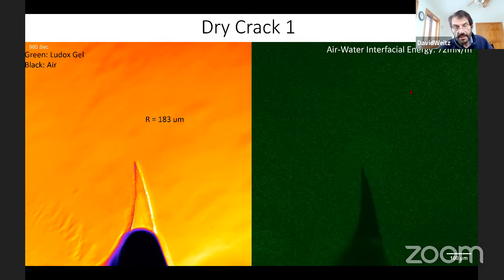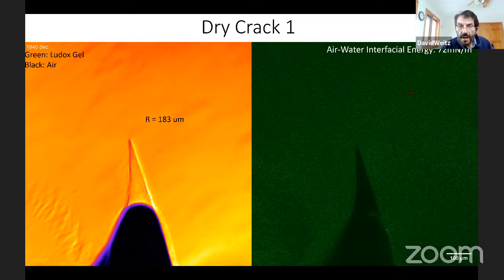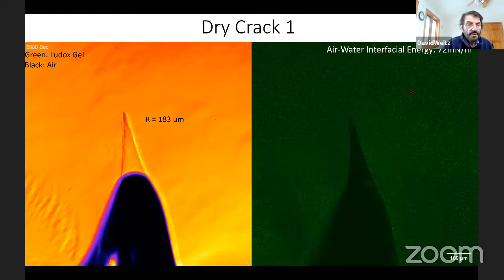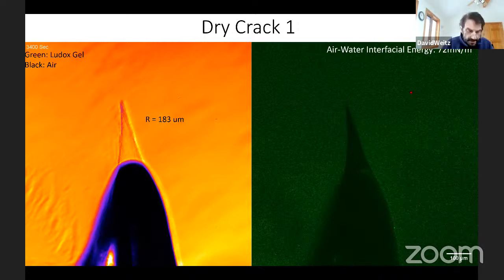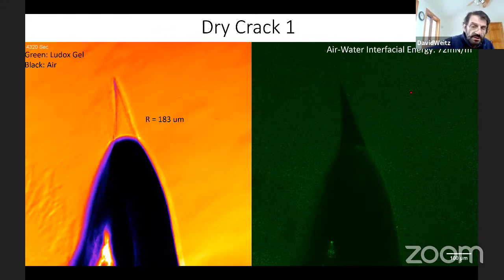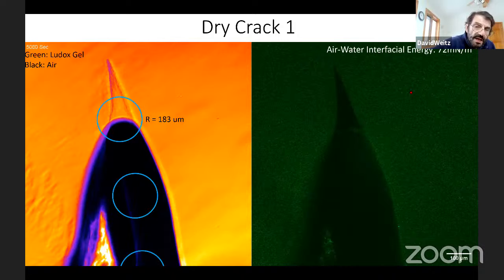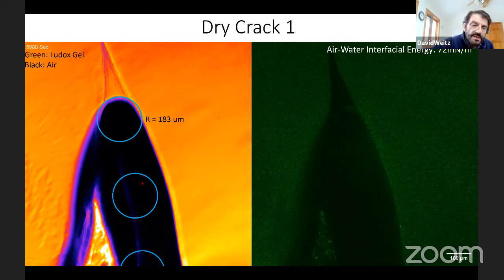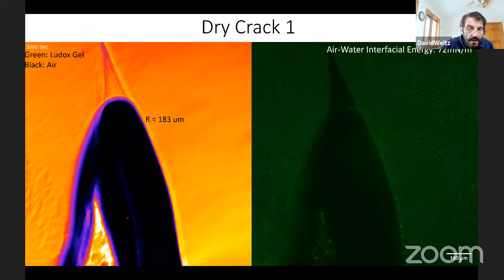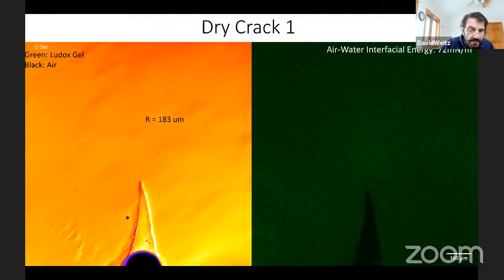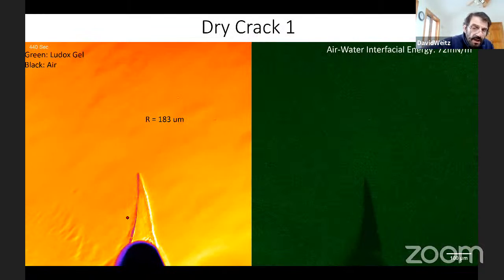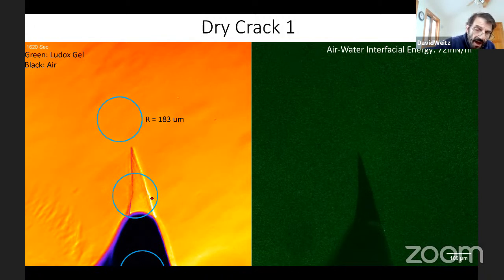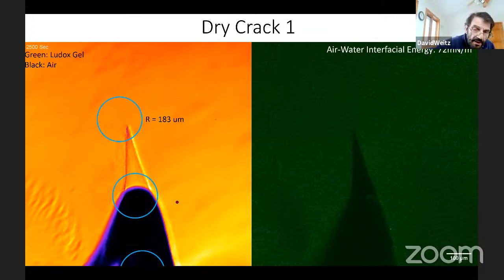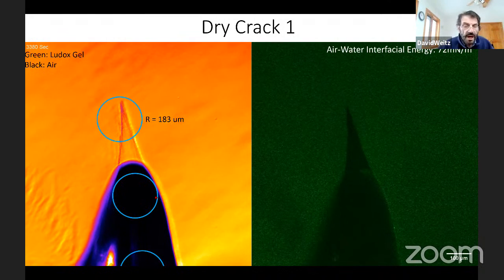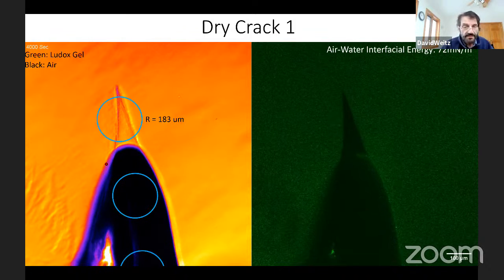On the right is the fluorescence, left is the real space. Again, the same sort of thing, but he plotted circles, and I put them before, but the radius of curvature is always the same. Now, let me see if I can play this again. I'll put the circles there a little earlier. You'll see that whenever these circles, that I or CG drew there, fit the interface, it's always the same radius of curvature.